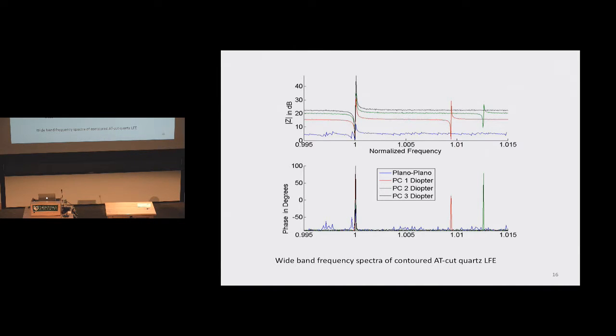It meant the following. This represents the planar information, and you see the excitation. This is the absolute magnitude of the impedance. This is the corresponding phase. You get a very tiny value over here and a tiny dip. As you began to make that top surface higher in terms of its curvature, in particular, 1 diopter being the lowest and 3 diopter being the highest, what happened is you got rid of the spurious response over here. You didn't have all of this low-level response associated with the planar, and lo and behold, you got a very strong impedance.